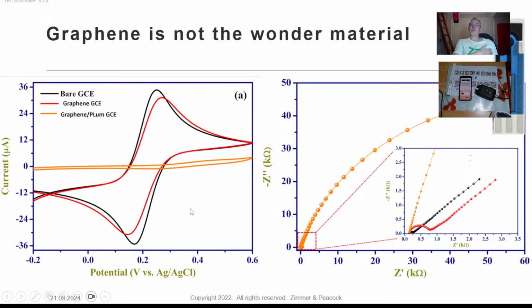So what that means is, it doesn't mean that polyluminol is not conductive. What it means is it's not very good at exchanging electrons with ferrocyanide. I had a look for the literature, and I'm not sure that I did find any. If this polymer was a bit more porous, so that the ferrocyanide could get through the polymer straight to the electrode, you probably would have a bit more of a signal. But I suspect you've got a very good coating of this polyluminol, and it's telling you if it's conductive, that's fine. But just because you're conductive doesn't mean you can then exchange electrons with the ferrocyanide,